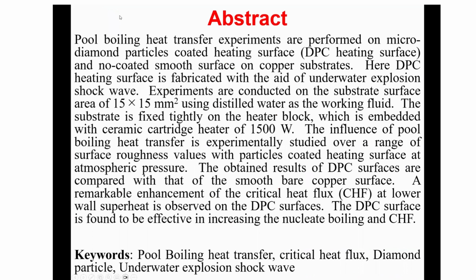First, I'd like to show the abstract. The pool boiling heat transfer experiment was performed on the diamond particle coating heating surface, the DPC heating surface, and the no coating smooth surface on the copper substrate. Here, the DPC heating surface is fabricated with the aid of underwater explosion shock wave. The experiment was conducted on the substrate surface of 15 by 15 millimeter square, using distilled water as a working fluid.